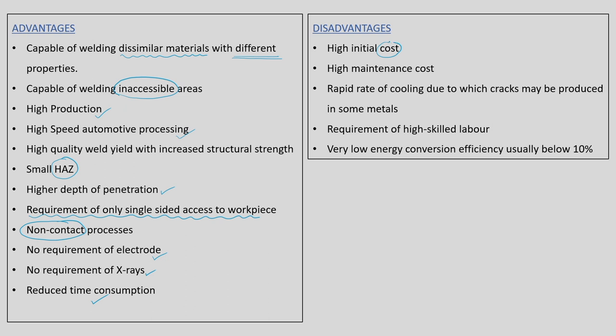Limitations of laser welding include: high initial cost; high maintenance cost for inert gases and instrumentation; rapid cooling of the weldment causing cracks in some materials; requirement for highly skilled operators; and high energy consumption due to the low efficiency of lasers — making optimization of process parameters essential.